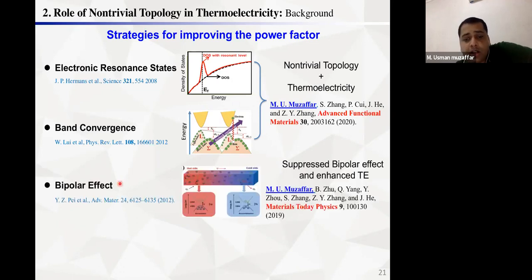So the third technique is the bipolar effect. Usually in small band gap semiconductors, at high temperature, we have majority carriers and minority carriers. So at high temperature, both the majority and minority carriers start conduction. The electrons have a negative Seebeck coefficient, and the positive holes have a positive Seebeck coefficient. When they start conduction, they mitigate each other. I mean, they cancel the effect of each other. So as a net, we have a very small Seebeck coefficient.